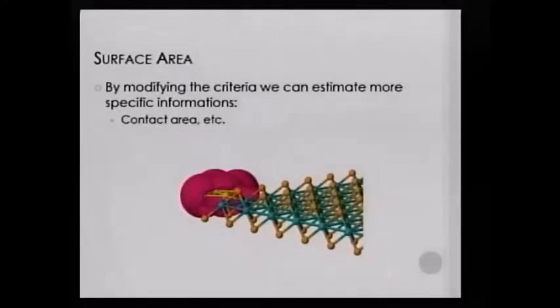Well, the idea is that, like I said before, the value of the surface area depends on the probe size, and, for example, you have the fixed value for the van der Waals radius of the atoms in question. However, if you use the same probe size for all the configurations you're studying, you have the same basis for comparison. Besides that, what you can use is to increase the density of the probing, so you can have more probes per atom in order to get more refined results. If you use few probes per atom, you have a very varied result.